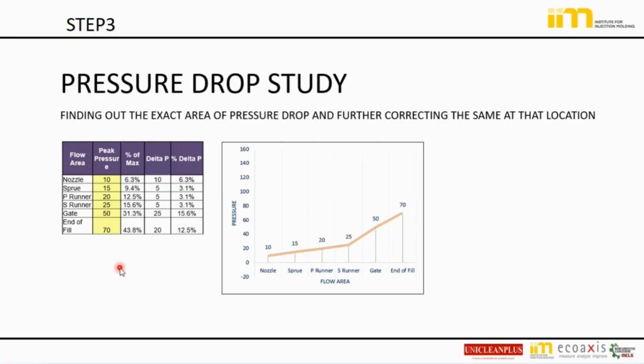So here we are studying whether it is within that range, first of all. Second, the thumb rule for the feed system is that for a cold runner, a pressure drop of 30 to 35 MPa is good enough. For a hot runner, it is more restrictive, so 40 to 45 MPa. If the feed system pressure drop is within 30 to 35 for a cold runner, and 40 to 45 for a hot runner, then the rest will come to our part. Suppose our feed system or gate is taking so much pressure, like 100 MPa, then our part will not get anything. Only the runners will look very good and shiny. That's not the point. Our part should get the proper pressure.